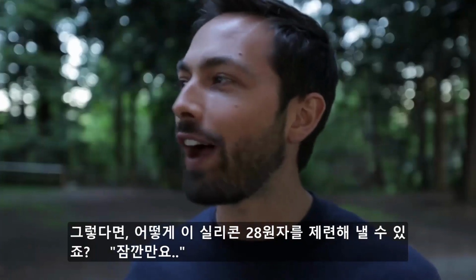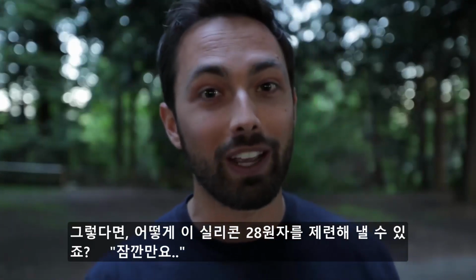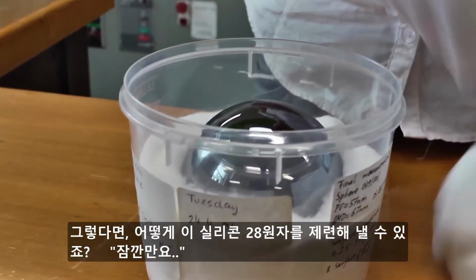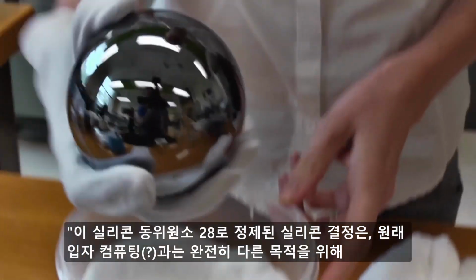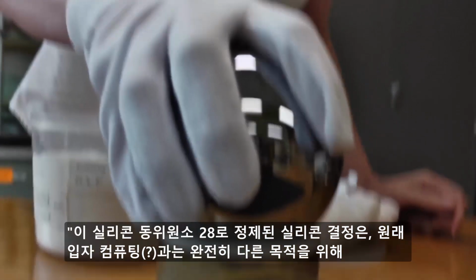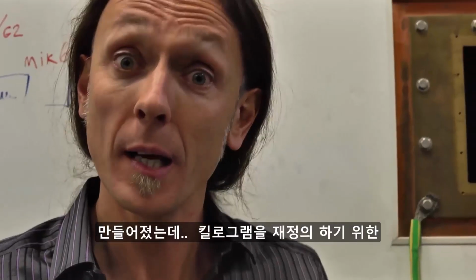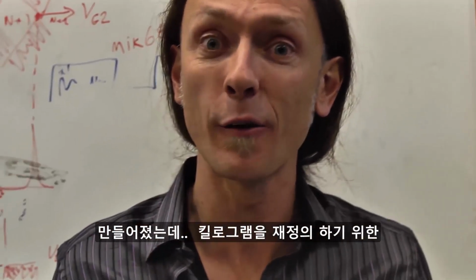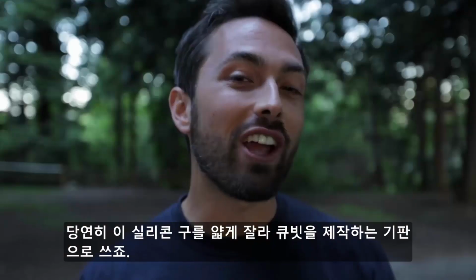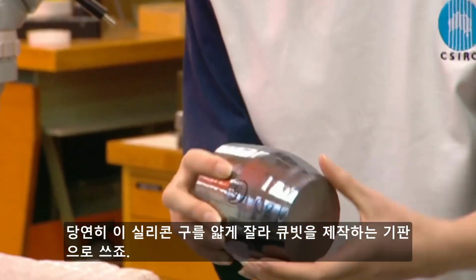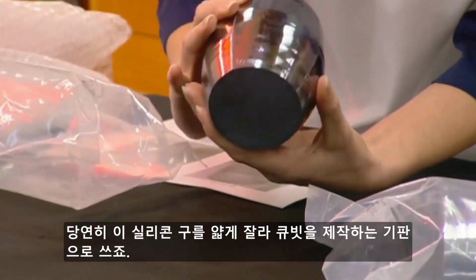But where are you going to find a pure crystal of silicon-28? Oh, wait. These isotopically purified silicon-28 crystals are being produced anyway for a purpose completely different from quantum computing. They're being produced to redefine the kilogram through the Avogadro project. So the offcuts from that silicon sphere are actually being used as the home for qubits.